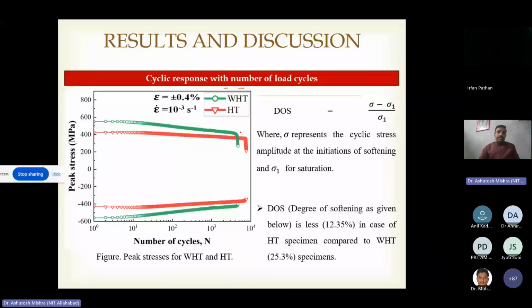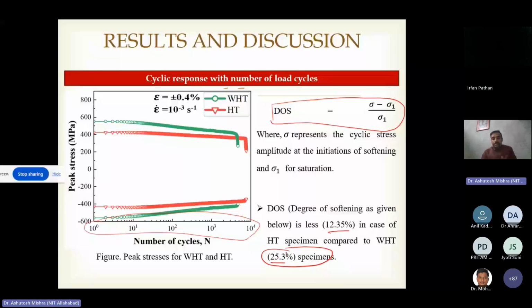Now, here we have again compared the peak stress. It's a slightly zoomed view of the earlier plot, that is peak stress variation with number of cycles, wherein the number of cycles are in log scale. Here, this particular information is used to calculate the degree of softening. The degree of softening is less than 12% for the HT specimen. And for the without heat treated specimen, the degree of softening is more. Now, if the degree of softening is more, it means the fatigue life is less. This is also as per the literature which is available, which is published.